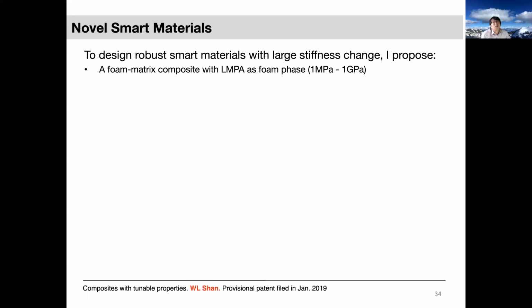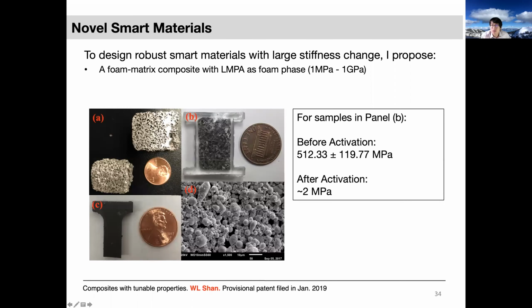Now, to design robust smart materials with large stiffness change, here I propose a foam matrix composite with LMPA as the foam phase. So we're gonna start with this LMPA foam to make sure the LMPA is well connected. And then we're gonna infiltrate this foam with elastomer. And this way, the material is gonna be bicontinuous. It will be very robust because we have this outside elastomer matrix, and it will be really rigid before activation because the LMPA foam is gonna bear all the mechanical load when it's not activated.